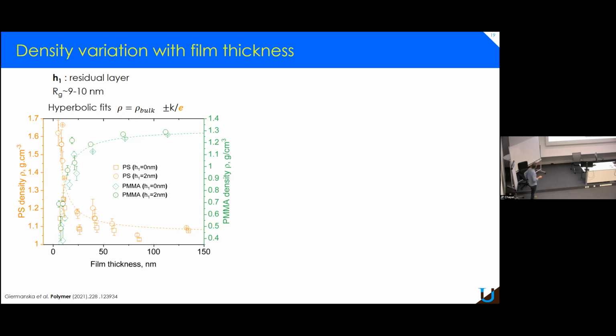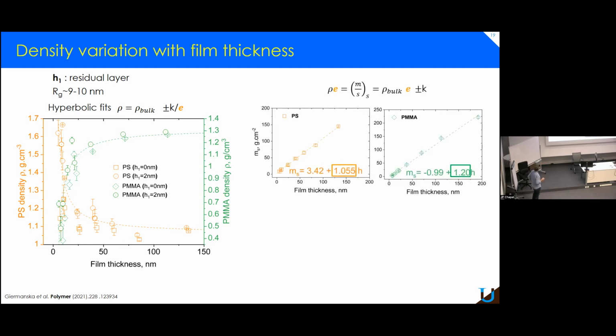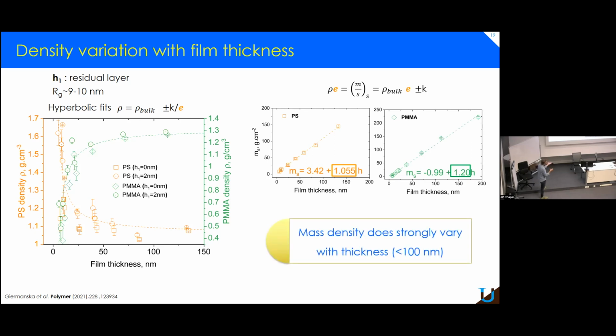So here what we say is that when we decrease the thickness of the polystyrene, the density can increase quite a lot, meaning up to 40–50%. I agree that the absolute value is maybe a bit difficult to understand, but at least the variation is obvious here. We were also able, from those data, to retrieve once again the bulk density using the same approach. So everything was somehow consistent here. So mass density does strongly vary with thickness, at least from the QCM.